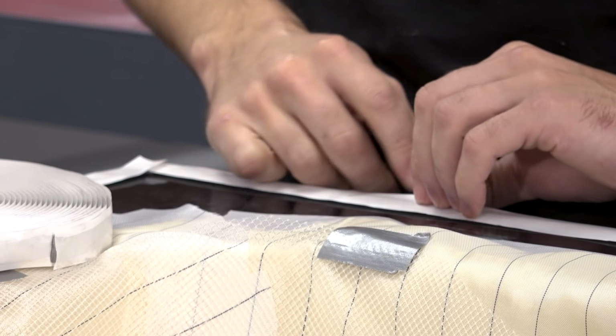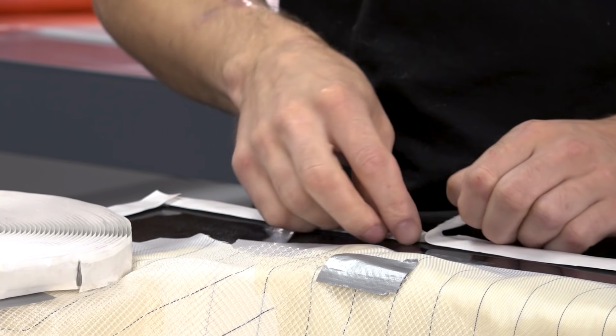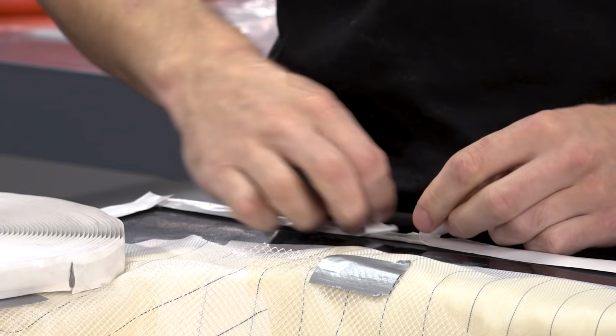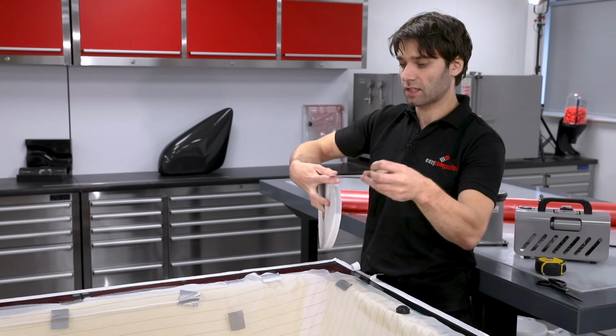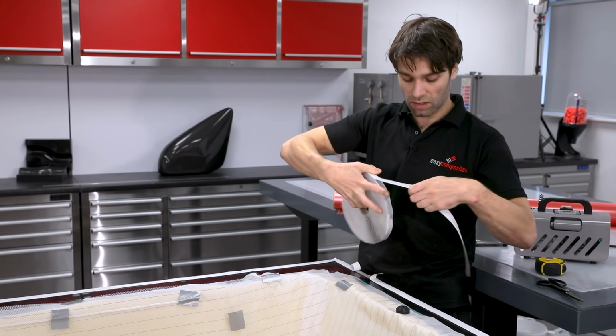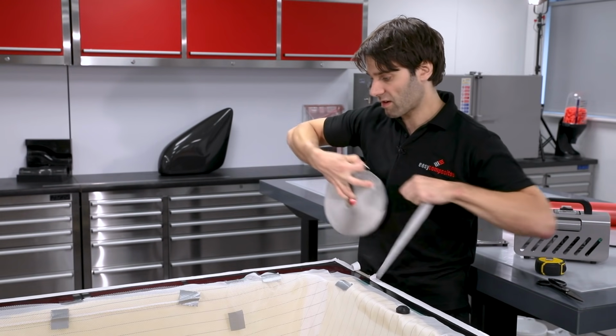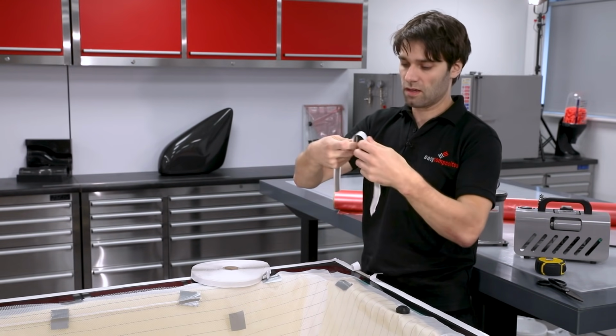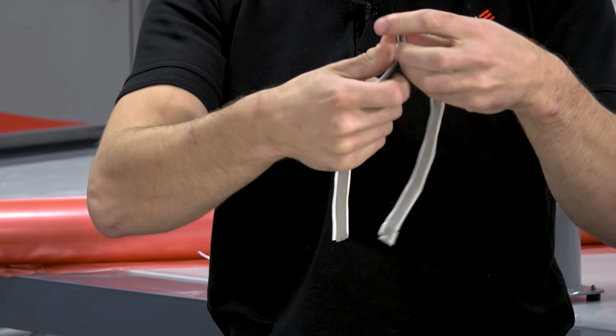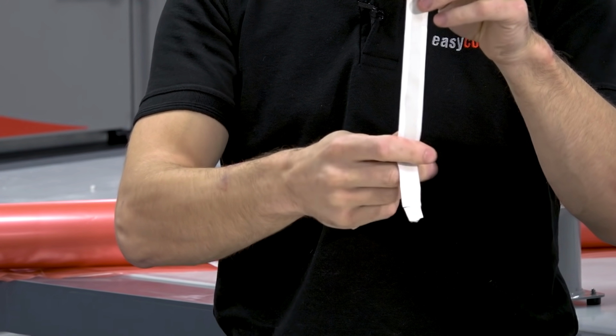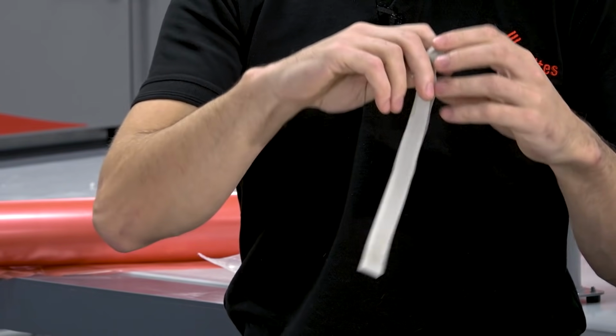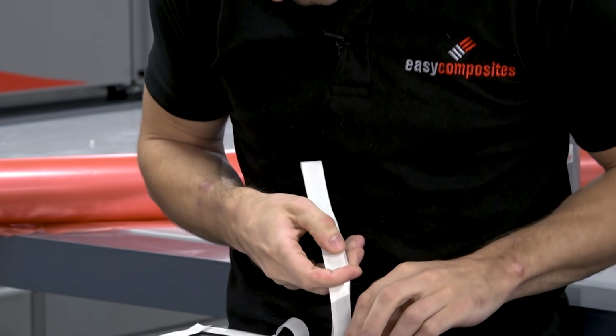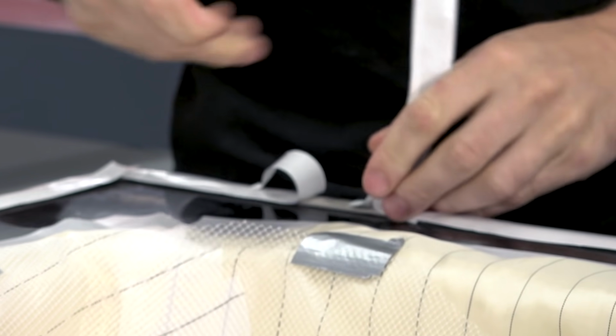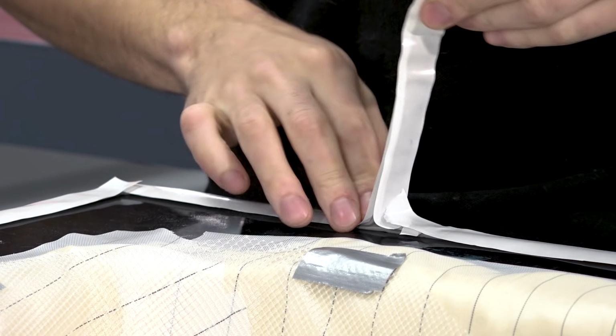Creating the pleats is very, very simple. Just tear off some of the backing off your gum tape. Take some more gum tape. So in this case, around about 400 millimetres to create a 200 mil pleat. Fold it over on itself, like so, leaving some little legs at the bottom. Attach that onto the other seal. And there we go, we've got a pleat.